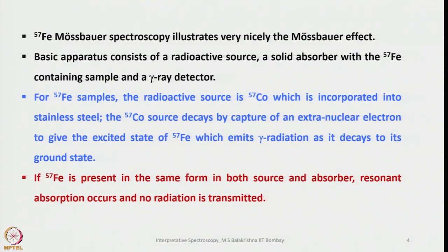And the basic apparatus consists of a radioactive source, a solid absorber with the Fe-57 containing sample and a gamma ray detector. Very simple assembly, Mössbauer spectroscopy. For 57 Fe samples, the radioactive source is 57 cobalt, which is incorporated into stainless steel. 57 cobalt source decays by capture of an extranuclear electron to give the excited state 57 iron, which emits gamma radiation as it decays to its ground state. So this is the simple technique we use in Mössbauer.